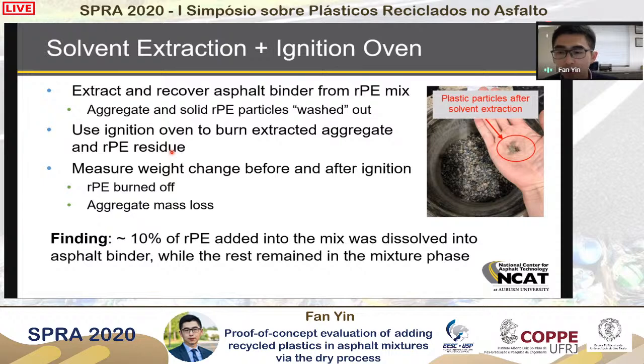In these small experiments, based on our calculation, we found that only 10% of the plastic added into the mix was able to dissolve into the binder, while the other 90% remained in the mixture phase. So this definitely provides some information about what kind of role recycled plastic plays in the dry process.